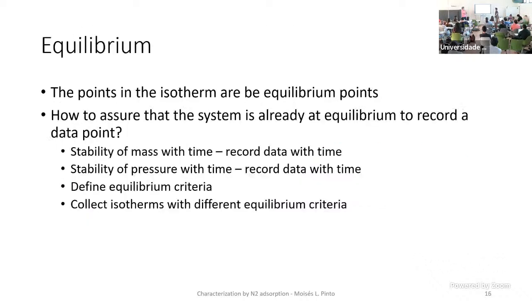So, like I said, the equilibrium needs to be reached. So isotherms are equilibrium points. And how can we know that the system is already at equilibrium? This is a big issue. Yes? If we have stability of mass with time, in a gravimetric system, then okay, you know it's already constant. But if you have stability of pressure with time, it can give you some idea, but sometimes it's very tricky because it's still adsorbing, but it's not so easy to see. So we need to define some equilibrium criteria, and of course, collect isotherms with different equilibrium criteria to see if they are reproducible. Okay?